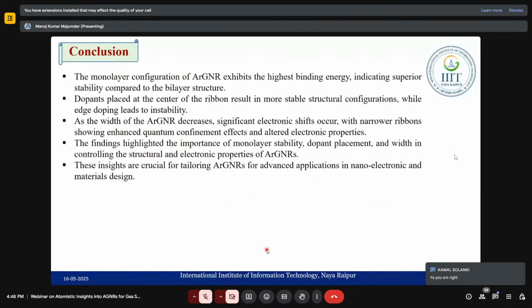And finally, these are the conclusions of this topic. Basically, as I told you, the monolayer configuration can exhibit the highest binding energy. Placement of the doping at the center of the ribbon can result in a more stable structure. And as the width of the AGNR decreases, significant electron shifts can occur. Okay, but it is good for the absorption energy.